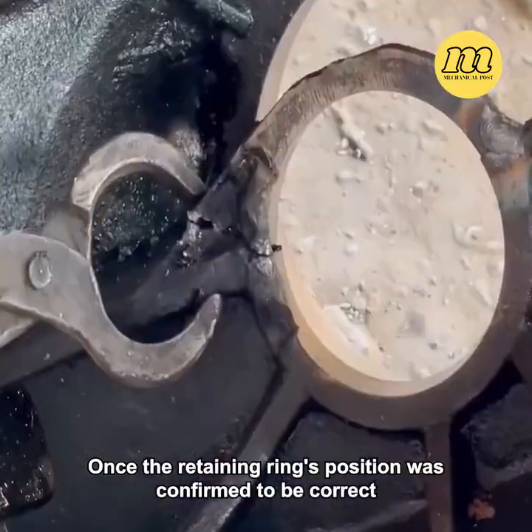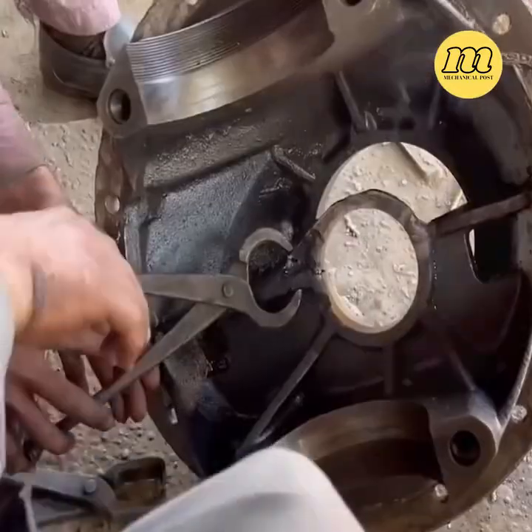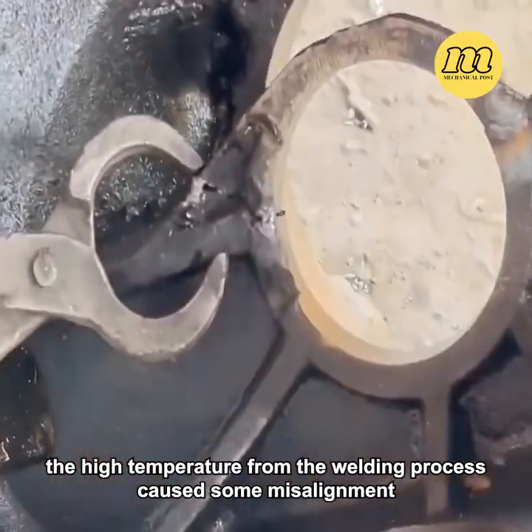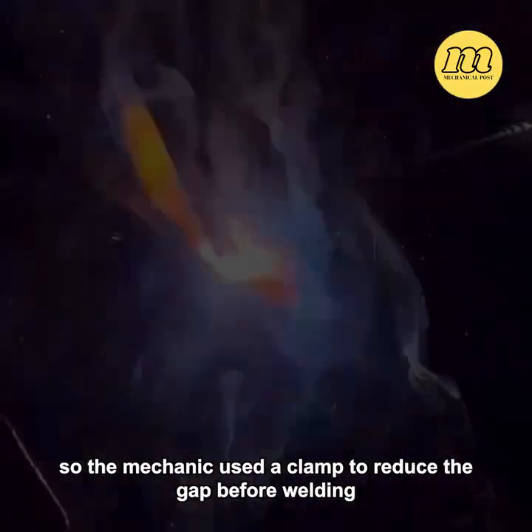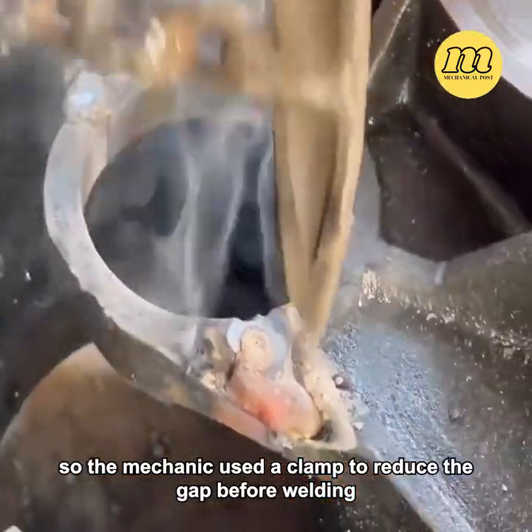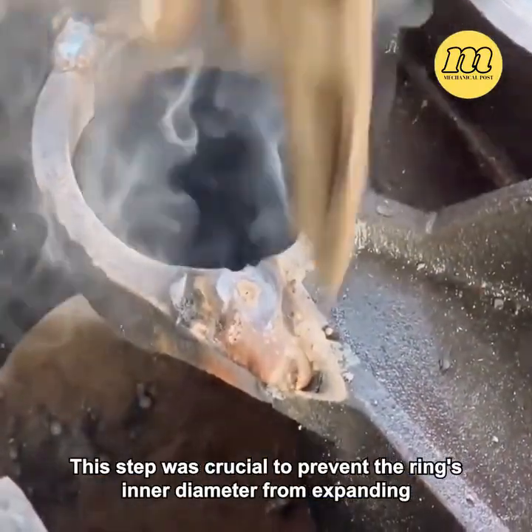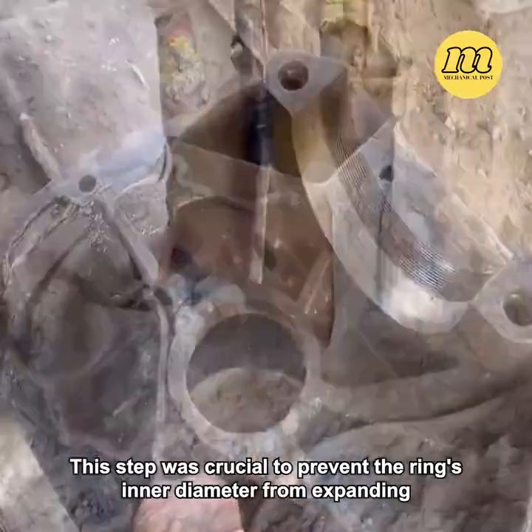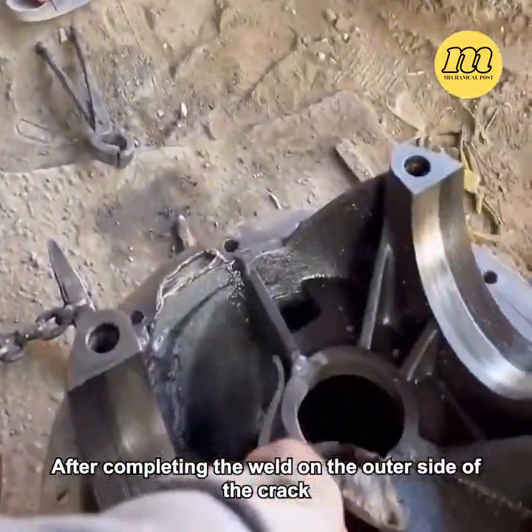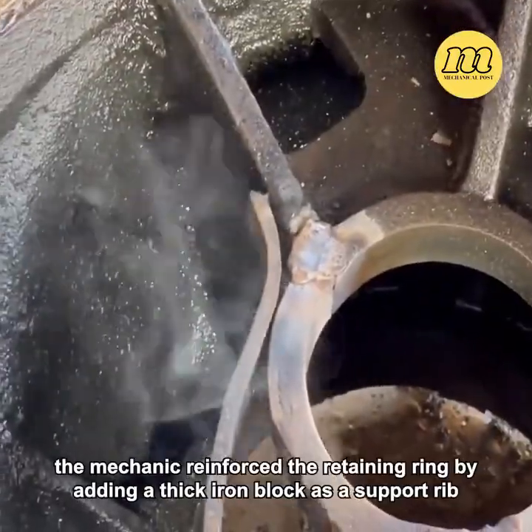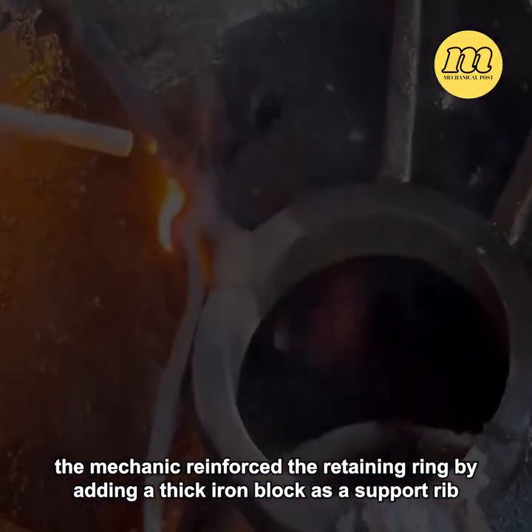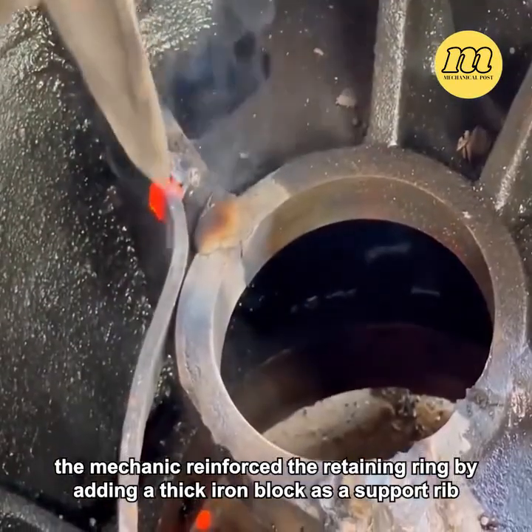Once the retaining ring's position was confirmed to be correct, the high temperature from the welding process caused some misalignment, so the mechanic used a clamp to reduce the gap before welding. This step was crucial to prevent the ring's inner diameter from expanding. After completing the weld on the outer side of the crack, the mechanic reinforced the retaining ring by adding a thick iron block as a support rib.